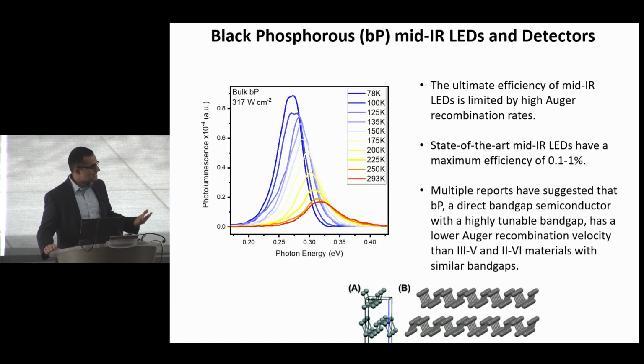And the reason is, as you shrink the band gap, Auger recombination shoots up dramatically. And so you're purely limited by Auger recombination. If you have a material of similar band gap, but with more symmetric electron and hole masses, then the Auger recombination rate can be dramatically lowered.